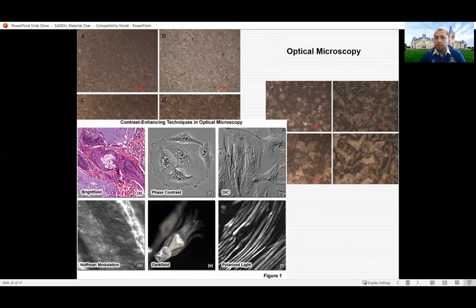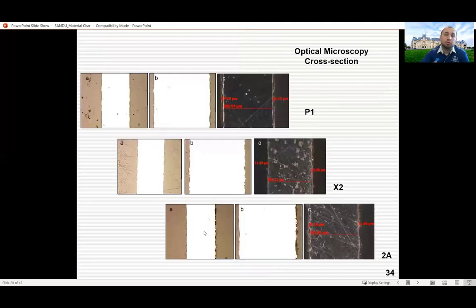And after seeing the devices, we have here some examples of results. We have the optical microscopy. These are some phosphate layers that are used in the automotive industry in order to protect the steel sheets that we manufacture the car from, to protect them from corrosion. And also we enhanced the lubrication of the surface in order, when you mechanically draw these sheets, not to destroy the surfaces. So if the lubrication is higher, then the protection against corrosion will be higher. Also, on different types of optical images, we can get here some cells in bright field, phase contrast, polarized light, dark field, Hoffman modulation, and so on.